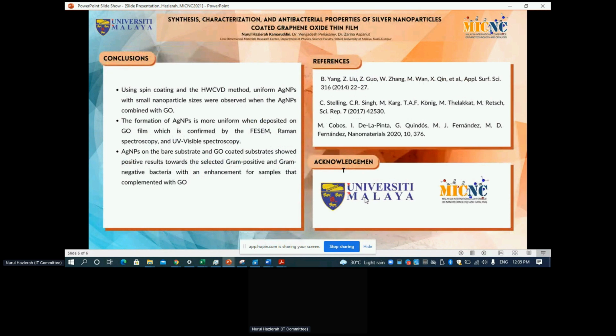And finally, as a conclusion, using spin coating and hot wire CVD method, we get a uniform size of silver nanoparticles with small nanoparticle size combined with graphene oxide. The formation of silver nanoparticles is more uniform when deposited on the GO, which is confirmed by the FESEM, Raman spectroscopy, and UV spectroscopy. Silver nanoparticles on bare substrate and GO-coated substrate show positive results towards selected gram-positive and gram-negative bacteria, with enhancement for the sample that was complemented with GO.